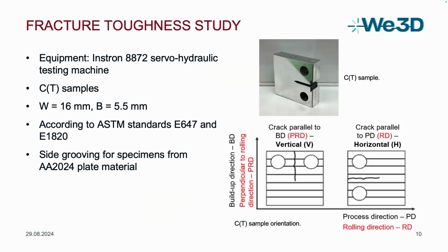For the fracture toughness study, we used an Instron 8872 testing machine and CT samples, as we can see here on the right side, W16 and B5.5, according to the standards 647 and 1820. Furthermore, for the 2024 plate material, a side grooving was necessary. And here in this picture, we can see the orientations out of the raw materials: according to the process direction for the wire arc material, and according to the rolling direction for the plate material. So we have the horizontal orientation, and perpendicular to it, the vertical orientation.